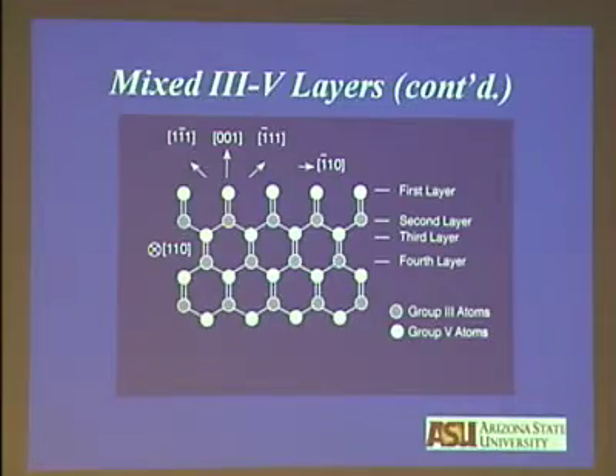So recapitulating what I showed you here, if you have size differences between the species occupying a certain sublattice in 3-5, the material is going to phase separate. There are no violations of that idea. In the case of indium gallium phosphide, the same thing happens. Indium and gallium phase separate for the same reason I described, and indium gallium arsenide does the same thing, which I will show you. And phase separation occurs along the soft directions, lying in the growth plane. It's the reduction in strain energy that is the driving force for phase separation. Phase separation produces two-dimensional strains in the layer, or two-dimensional biaxial stresses that cause buckling and give you the dark bands I showed you.